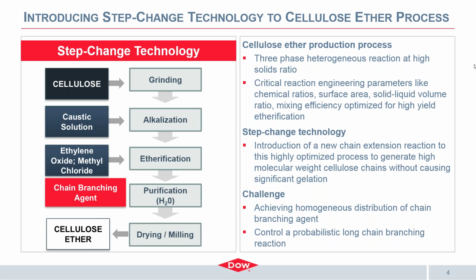The chart on the left schematically depicts how cellulose ethers are produced. You've got ground cellulose at the top left, and then this is reacted with sodium hydroxide. That's the alkalization. Then we add ethylene oxide and methyl chloride. That's the etherification step. Then there's purification, and the material is finally dry milled, and we end up with the water-soluble cellulose ether. And our new process includes one additional step that's highlighted in red. That's where the chain branching agent is added to produce chain branched cellulose ether.